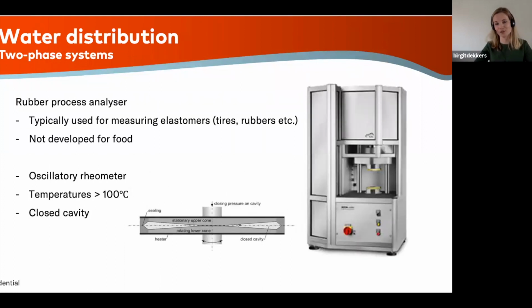Therefore, we're using a rubber process analyzer, which is maybe a bit of an odd thing, because this rubber process analyzer is, as you can imagine, not developed for food, but for rubbers, elastomers, tires, these types of things. This was quite a big challenge, because the people that we were usually working with on these types of devices didn't hear anything about food and never experienced working with food. But it was a very nice device for us to work with, because it could measure rheological properties above 100 degrees in a closed environment, in a closed cavity. And thereby we could measure these rheological properties in a good way.